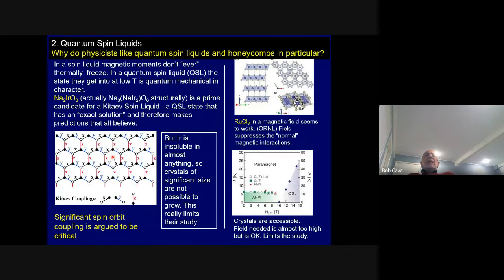So I think that right now we have quantum spin liquids, which fits right into your quantum aspirations. And I think that the first one that I know that was illustrated to do that, the first material was sodium 2 IrO3, which is like Na3NaIr2O6, which is a honeycomb lattice of iridium, and iridium 4+, which this is based on, has one unpaired electron. So if you put that here and here, if we extract now the magnetic lattice from this crystal structure, this magnetic lattice has a honeycomb.